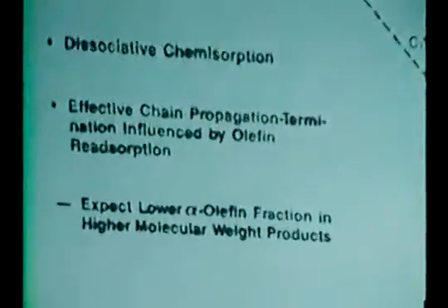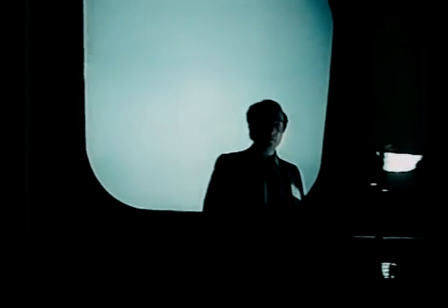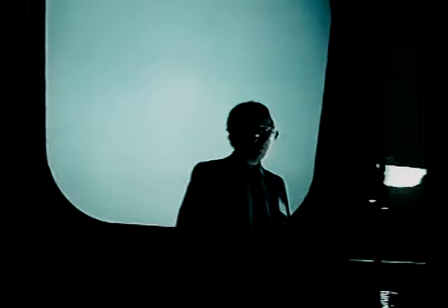Okay, I'm going to describe some very early and simple experiments that we did. We've done these in a CSTR in an autoclave environment, completely back-mixed, at reaction pressures of about 5 atmospheres with 2-to-1 hydrogen to CO. Initially what we did was take some Fe3O4, which had been sintered at between 400 and 500 degrees C. We loaded our CSTR with this iron oxide and looked at its behavior. We took the catalyst out after the reaction, did X-ray diffraction on it, and after a period of about 40 hours in the reaction, we found that we were still able to maintain Fe3O4, at least as a bulk phase.